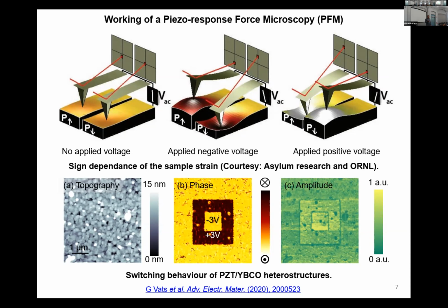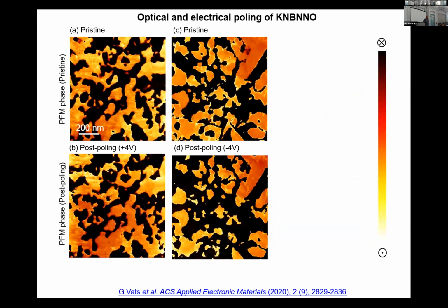Yeah, so let's look at some of the results. Before that, I should explain what I actually did. I had a ceramic sample, which was 100 microns thick. I put that sample here with an AFM tip in contact, and I used a laser source to shine light on the sample. Firstly, I did this electrical poling experiment. You can see this figure A. This is the image I acquired in dark. Again, the bright yellowish domains and dark domains mean polarization pointing up and pointing down.